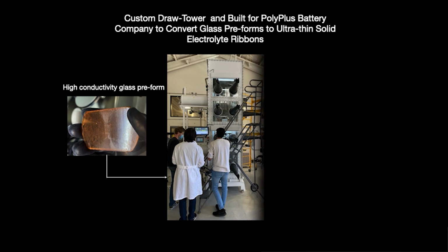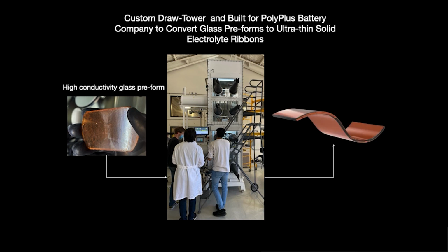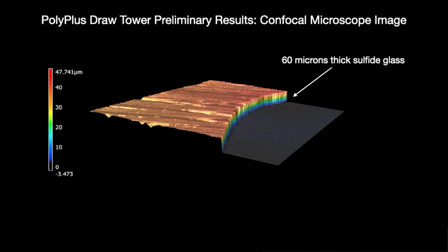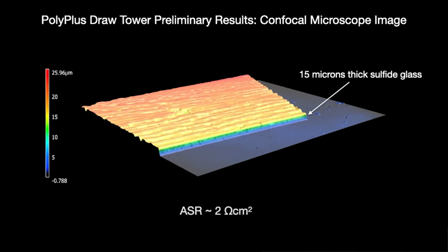So just to blow that up a bit, this is actually a sulfide glass preform. We're now making larger preforms, but in any case, that preform is large enough to take into the draw tower. And the tower, as you see there, is obviously protected from the environment while we're drawing the heated glass. And then there you see, in fact, that's the ideal, to pull out thin glass. If we look at the glass coming out of the draw tower with a confocal microscope, you can see that we very quickly get down to 60 microns, and pulling a little further, we're pulling glass all the way down to 15 microns thick. That is an ASR of about 2 ohm centimeters squared.